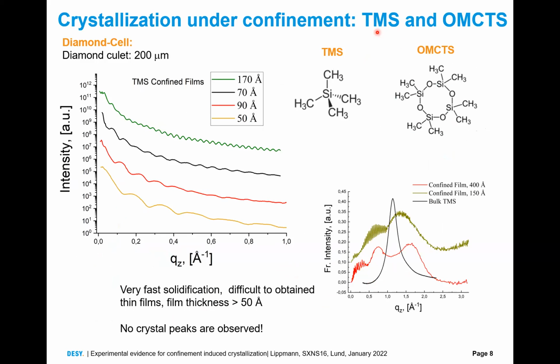Here I present the results of OMCTS and TMS. Actually, mainly from TMS, but the OMCTS behaves in a very similar way. I have to say that this liquid solidifies very fast, and evidence for this is that the thickness we get when we confine is defined by the amount of liquid we have on the substrates. And once we get this film, it is very difficult to compress it further.